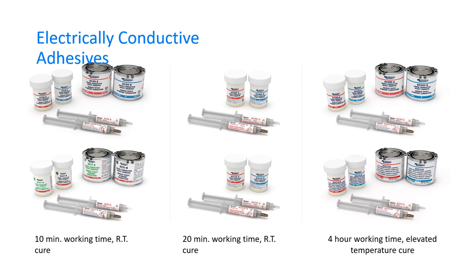And then finally, on the right, we have the 4-hour working time, 8330S and 8331S. S is for slow. But these do not cure entirely at room temperature. You do need to heat cure them. If you're looking at minimum temperature, we could probably get away with as low as about 50 degrees Celsius to initiate that final degree. They will reach a state of cure at room temperature, but not fully cured. So you do have to add heat to post-cure and reach that final cured state.